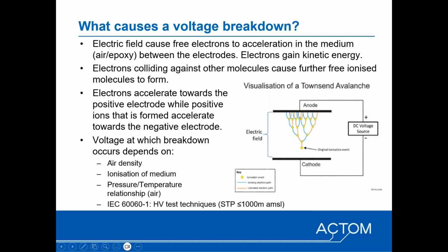The voltage breakdown, or the voltage at which breakdown occurs, depends on the air density. So if you have a low air density, for instance, at high altitudes, the spaces between the molecules are big enough for the electrons to gain enough kinetic energy, so that you don't need a high voltage to accelerate the electrons to create a breakdown. At high air densities, for instance, at low altitudes, the space between the molecules is very small. Because of the denseness of the air, you don't have enough space for the electrons to gain enough kinetic energy to release electrons.